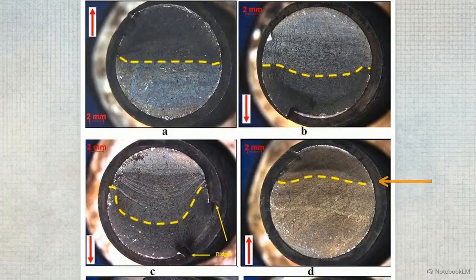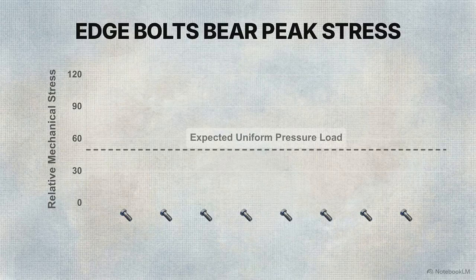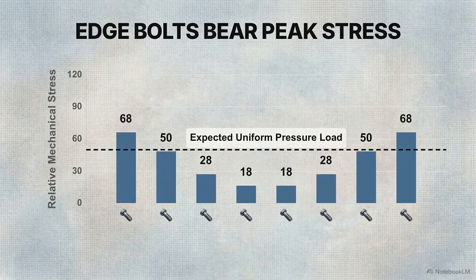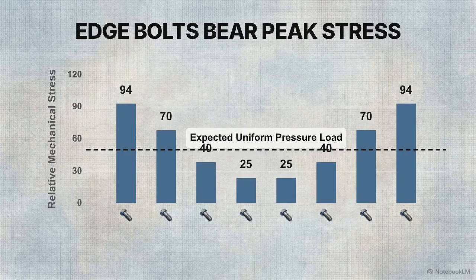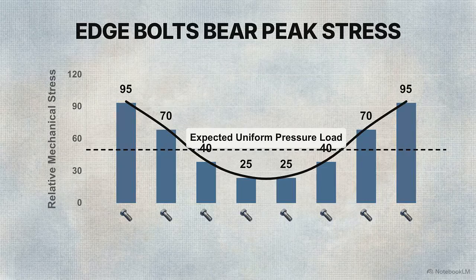Tracing the pattern outward toward the edges, across panels D, C, B, and A, the dashed yellow line drops progressively lower. The final fast fracture zones grow significantly larger the further you move from the center. This reveals that the mechanical load on the joint was heavily non-uniform. The stress distribution formed a distinct U-shape, peaking at the outer edges, a pattern completely inconsistent with the even outward push of a standard pressurized seal.